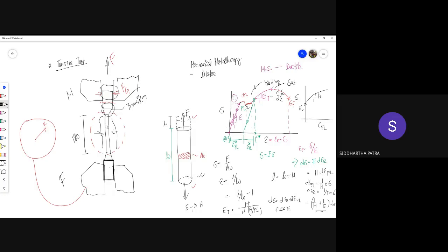Now, to have that happen within this portion, we can only use the one-third central portion of the geometry, and that is about 60 millimeters. That 60 millimeter becomes our gauge length L0. But this 180 millimeter is our capital L0, that we would use for a different purpose. This L0, as we discussed, would be used for calculation of the strain. This gauge length would be used for calculation of the strain.